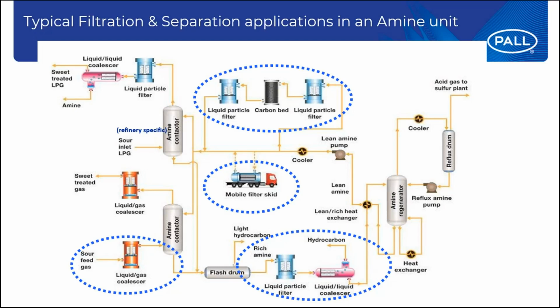We can act on the sour gas by a well specified and designed liquid gas coalescer. In the rich side of the amine loop, we might also have a solution that directly intercepts those contaminations, especially the liquid hydrocarbons, by means of a liquid-liquid coalescer. And then in the lean amine side, which is a more traditional location, we may have on a slipstream a liquid particle filter. Usually it is followed by an activated charcoal bed, which is also followed by a guard filter downstream of it, and usually this is handling up to 25% of the loop capacity.